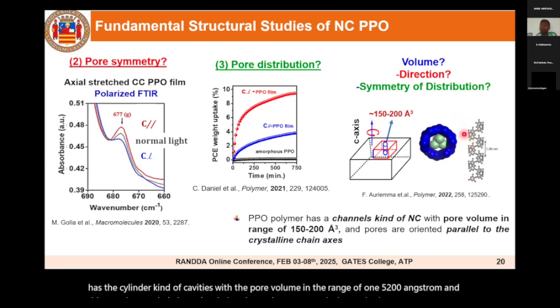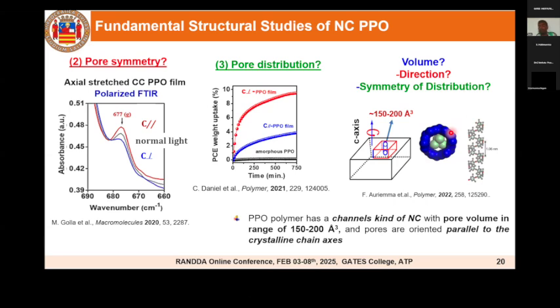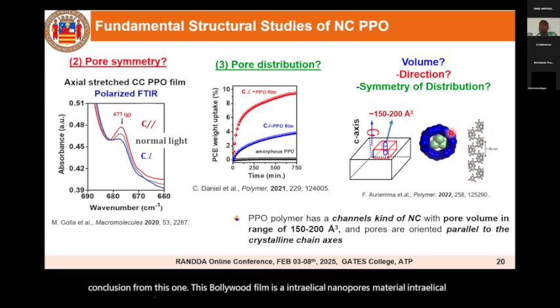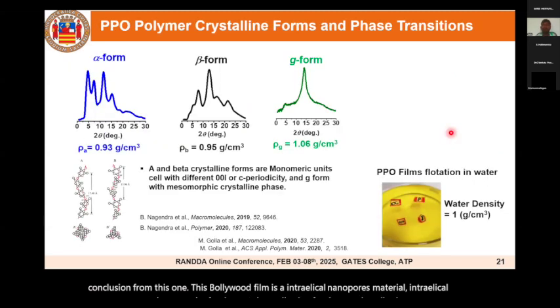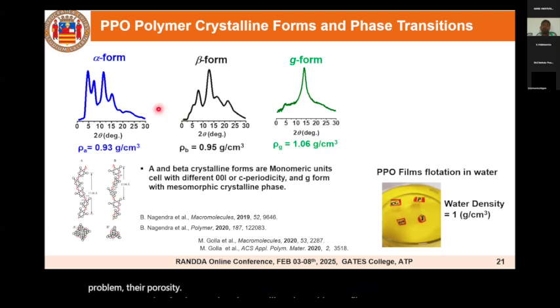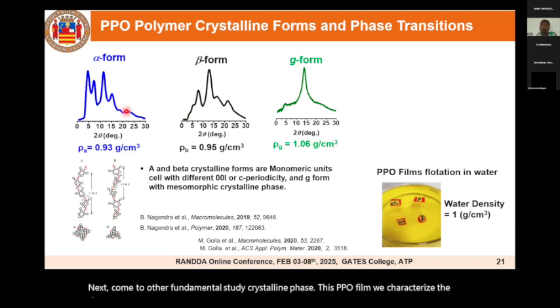Another important conclusion from this is that this polymer film is an intra-helical nanoporous material. So these are the fundamental studies of the PPO polymer and its porosity. Next, coming to another fundamental study, the crystalline phase. This PPO film, we characterized with three different crystalline phases. We named them alpha, beta, and gamma crystalline phase.